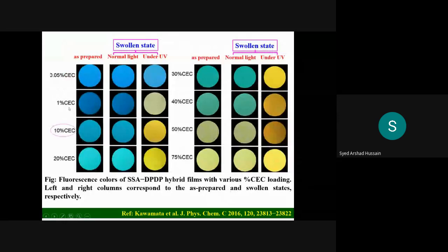So using the self-standing film technique, we prepared films at different concentrations. This first column is the image captured with a simple normal camera, maybe a mobile camera. These are organic hybrid films prepared with saponite and pyridinium at different concentrations. This is 0.05, this is 1% of CEC, this is 10%. Percentage of CEC means if the clay can exchange 100 cations, then we exchange 10 cations, that is 10 charged dyes, so this is 10% of CEC, then 20% of CEC, then again this line, you see 30%, 40%, this kind of thing. This is just a simple image taken by a mobile camera just after preparation.